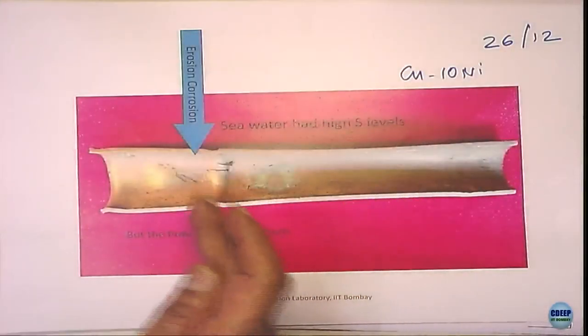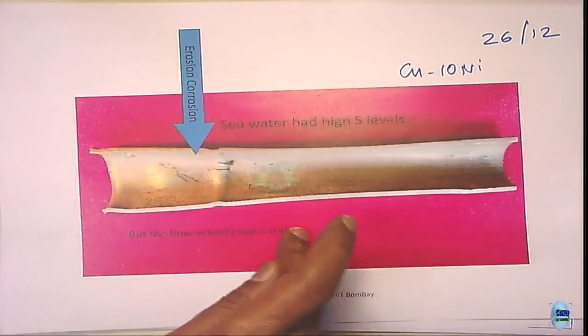And moreover, there is one more problem. When you take sea water, if you do not use a filter, as you said rightly, about 30% of the tubes were clogged because of some plastic, something happened. So when they opened up, they found that these are all blocked. That means only the remaining tubes are operating. So the actual velocity is not just 1 meter per second. It will increase further. So that adds more complexity to the problem.